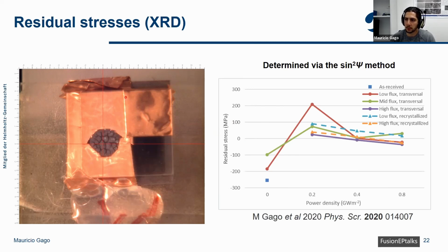So here we have one sample which was covered in a copper foil. This is so that the signal from outside the laser spot doesn't interfere with the signal of the laser spot. And we can see that the transversal samples start with compressive residual stresses in the surface, and these compressive residual stresses actually cause the sample to have a higher cracking resistance.